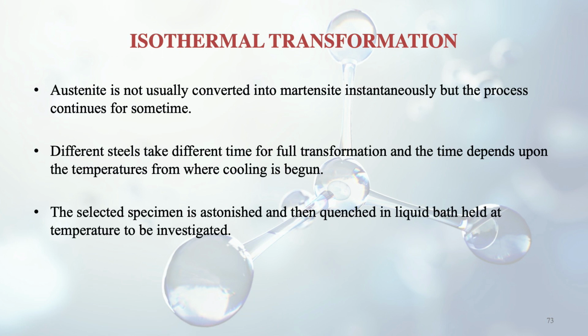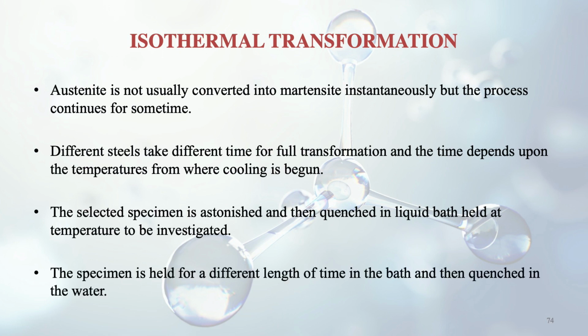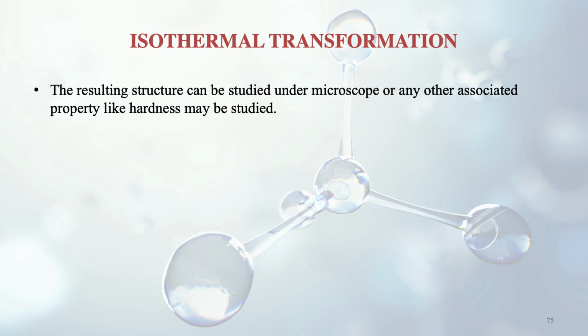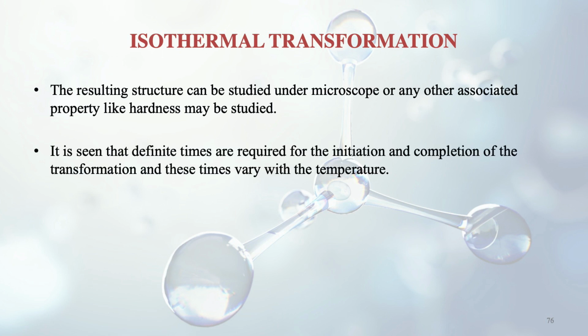The selected specimen is again austenized and then quenched in a liquid bath, held at a certain temperature to be investigated. This specimen is held for different lengths of time, like I have discussed earlier, that both temperature and length of time are very important. Thus the resulting structure can then be studied under a microscope to get the hardness and any other associated property. It is seen that definite times are required for the initiation and completion of the transformation, and these times vary with temperature. So if you can recall from the time transformation diagram, at different temperatures the time taken for transformation were different. So the same thing is given here.